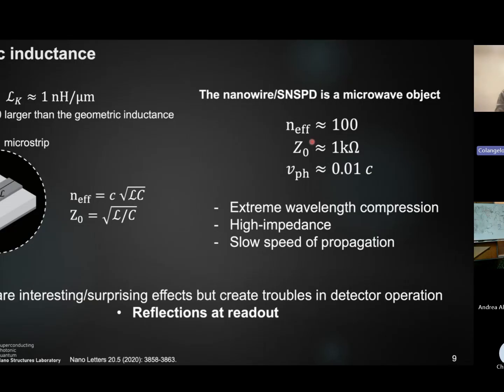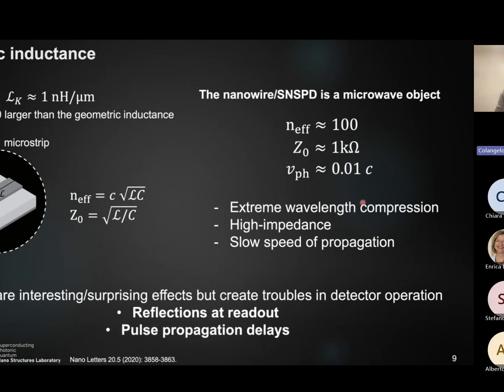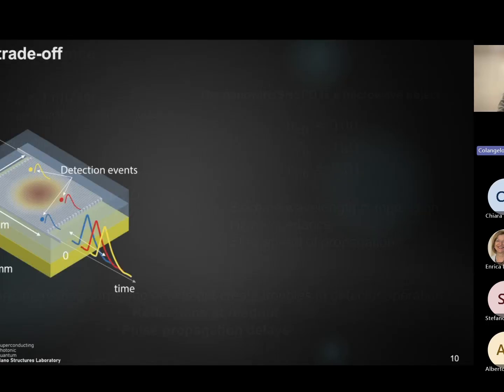high impedance means that when we interface that to the 50 ohm, we have reflections and there is no escape from that. And this slow speed of propagation means that we do have pulse propagation delays across the area when we use this detector. So now, how do we solve this problem?